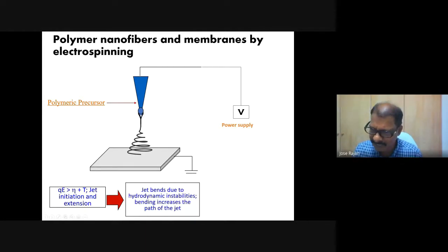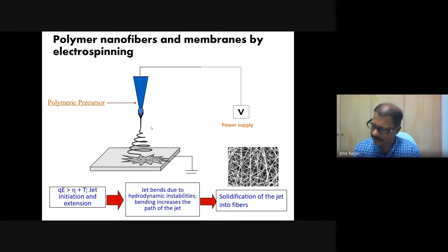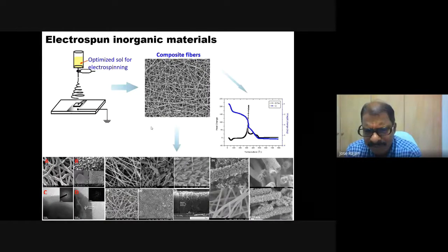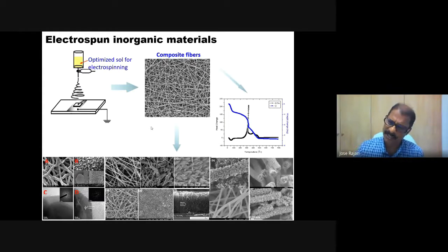Not only polymers, we can get almost any type of inorganic material also using electrospinning in diverse morphologies. If you know a little bit of chemistry of crystal growth from saturated solutions, you can play with this technology to create a number of morphologies. We have created in our laboratory not only nanofibers, we made big cauliflower-like crystals, multi-nanotubes, and more recently cuboidal shaped crystals on a larger scale. And people have come up with something like rice grain, nanotubes, and nano rods assembled on a fiber using electrospinning.